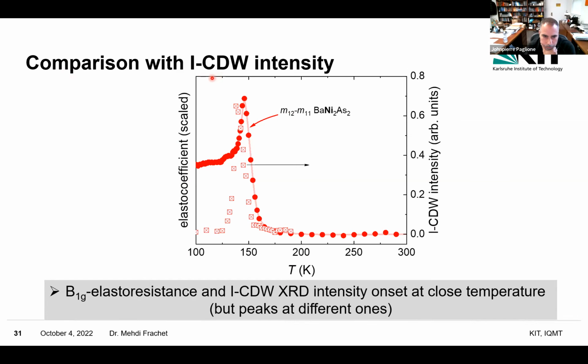Sorry, can I ask a question? Yes, sure. So just to be clear, this is for x equals 0, right? Yes. You're saying there's a peak in this susceptibility at the orthorhombic transition. Yeah. And there's not much happening at the triclinic transition? No, I don't see much. This is very different from what we observed in our paper. In our paper, we see, similar to the red data you're showing here, a continuous increase to the triclinic transition.